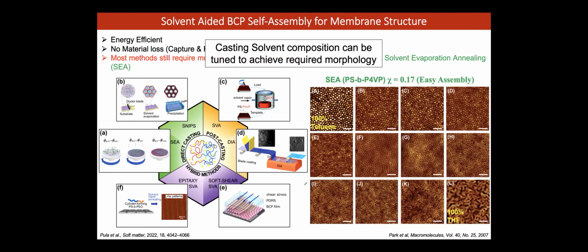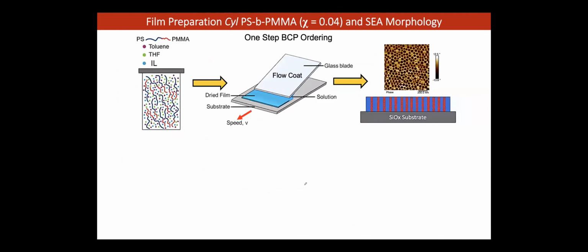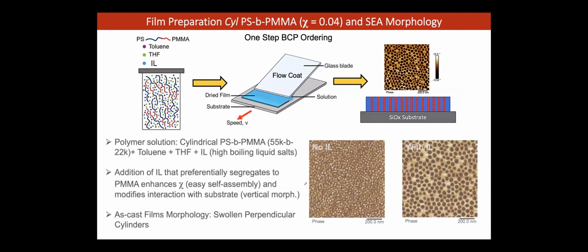We thought, can we do something with ionic liquids? Ionic liquids are non-volatile liquids, and Tim Lodge from Minnesota really popularized them, with a lot of work. We found that Ned Thomas did as well. These ionic liquids have selectivity in terms of which polymer they end up in, and they can be very fast.